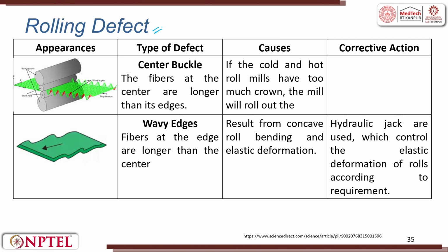But rolling also is not straightforward, it produces a lot of defects. In the appearance it will be like this. This one is called center bulging. If the cold or hot rolled mill has too many crowns, the mill will roll out and it will have a center buckle. This is a waviness which is created because of residual stresses which are there. The fibers at the edge are longer than the center one. So, it tries to create the waviness. Okay. So, these are some of the defects which come out of the rolling process.